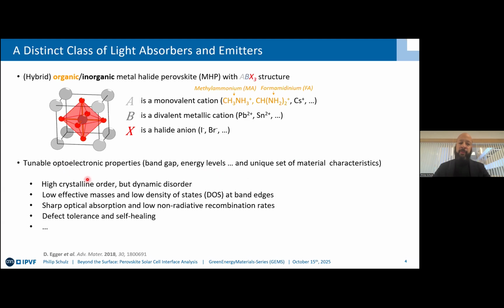In the materials we observe high crystalline order, but they also feature dynamic disorder. They have low effective masses and low density of states at the band edges, which makes it particularly difficult to determine the band offsets, something that has been plaguing us electron spectroscopists in the analysis of these materials. And then, of course, there are sharp optical absorption edges and low non-radiative recombination rates, except, of course, if you manage to introduce some defects, though the materials can be defect tolerant and even show some sign of self-healing, or better, self-repair.